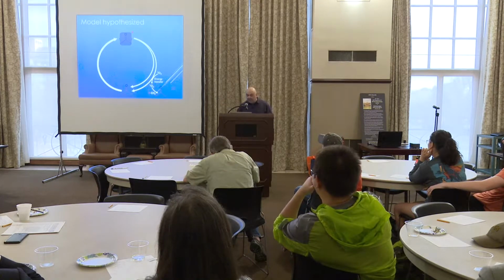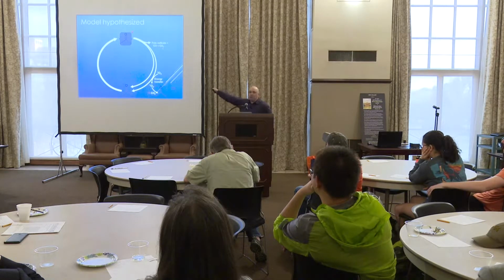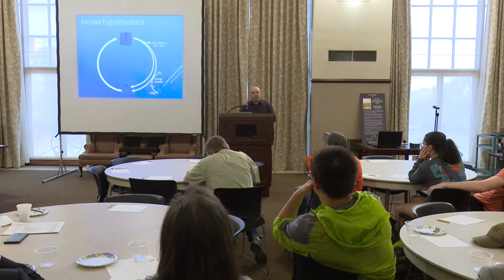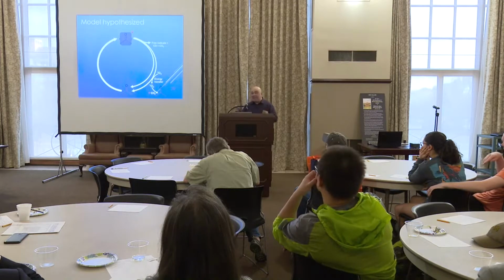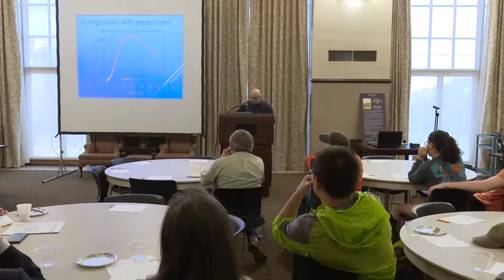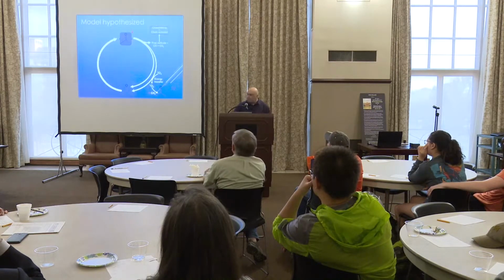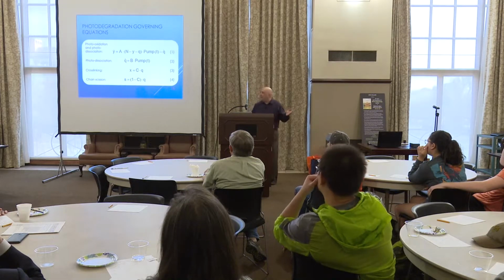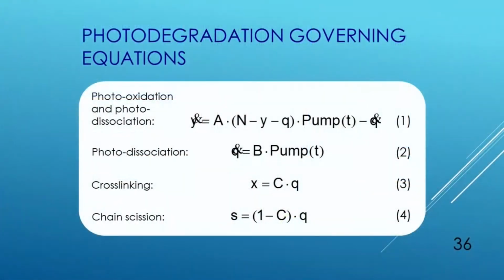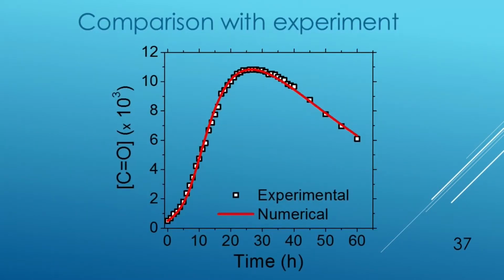So this was the basic model we hypothesized. And the carbonyls, if they don't do this and if they don't do that, they can also dissociate to carbon dioxide, monoxide, and that's really the volatilization of the polymer. So this was our actual model, and what needed to be done is just to validate this. So what we did was, we put this picture, this model, into mathematical equations. So we came up with 4 coupled differential equations. And if you solve number 1 and number 2, you can solve the other 2. And we got a pretty good agreement with the experimental data. And in this solution, we only have 2 rate constants. It's not really fitting. The equations were pretty ab initio.